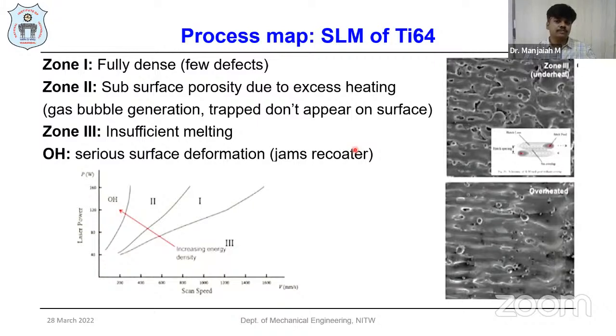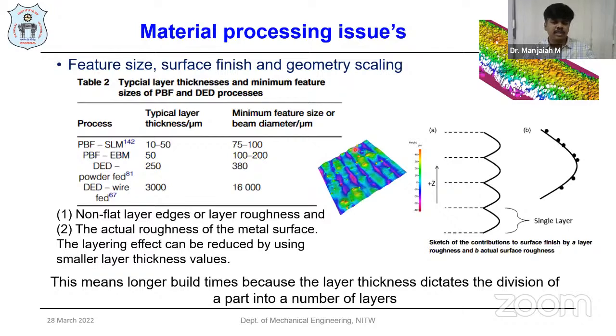These kinds of defects are going to occur if you are not optimizing the process parameters to melt the materials. And the other processing issues are material issues, like feature size, surface finish, and geometric scaling. We assume that each layer is in this fashion, whatever layer we define, either 40 micron or 20 micron or 10 micron. It will have this fashion. This kind of stair stepping effect will be there. Non-flattened layer edges will be there. It has a very rough surface finish. The actual surface finish of the metal is like this, but we are assuming this. They actually will have this kind of metal surface, because there might be some chance of unmelted or partially melted particles which stick to each layer. This will accumulate and it may affect the overall geometrical defects.